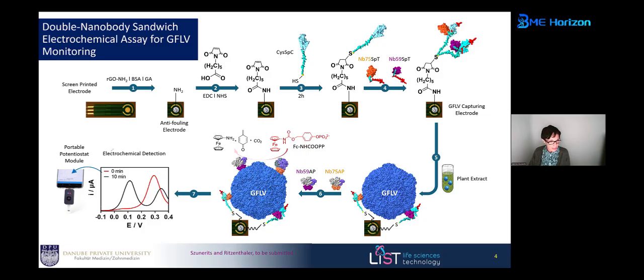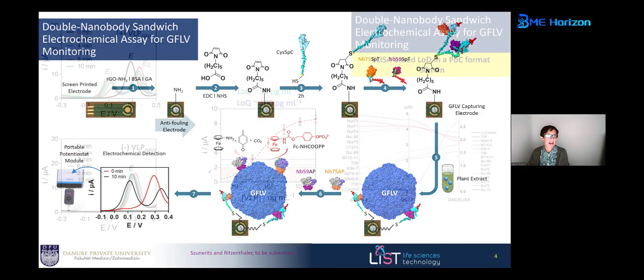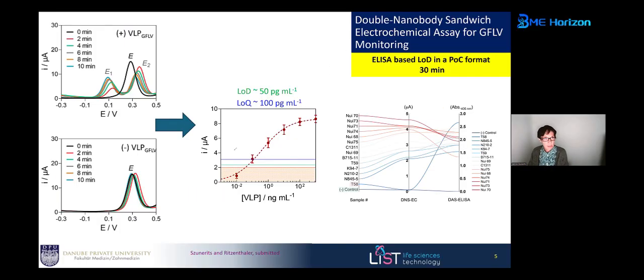And what you see here in the differential pulse voltammogram is that the initial product has a redox couple peak at around 0.3 volt, whereas the product is much, much lower, around 0.1. That means we can rather easily detect the onset of the occurrence of the product in case there is a virus particle present. And to show you that this is a viable approach, here are some of our data.